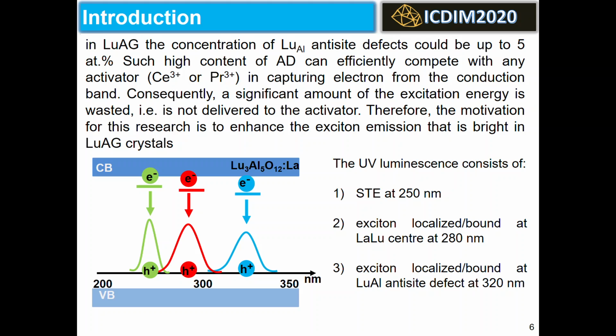Therefore, the motivation for this research is to enhance the exciton emission that is bright in LuAG crystal. Lanthanum doping into the LuAG lattice can cause the displacement of small-size lutetium cations from the dodecahedral positions into octahedral positions, thereby increasing the concentration of lutetium-aluminum defects.